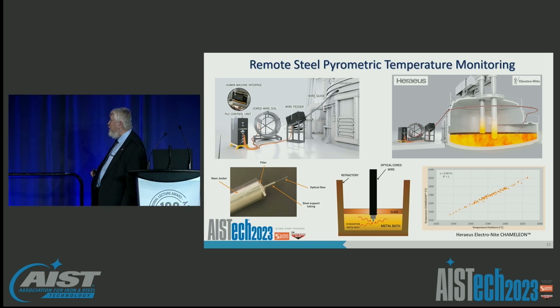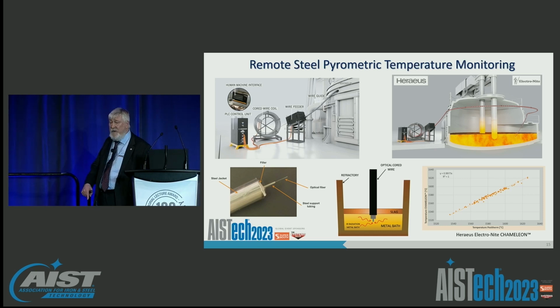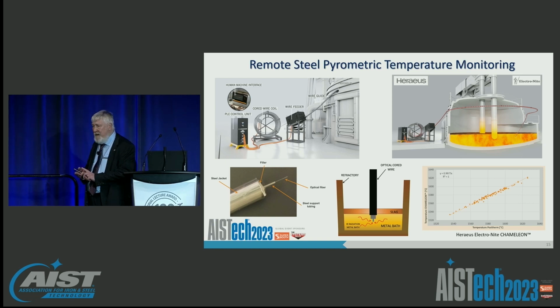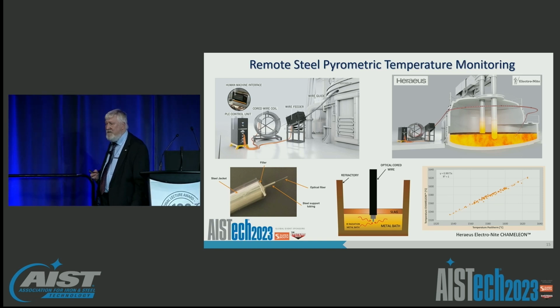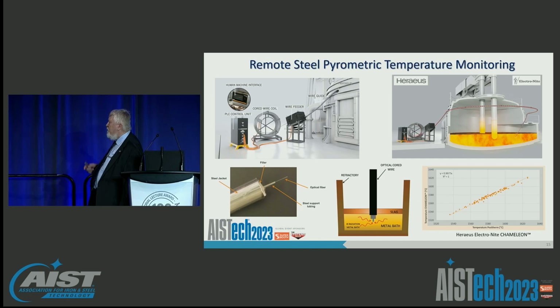There are some other advantages of this system. Because the fiber is being introduced and consumed, we can also do things like track interfaces, such as slag and metal bath heights in these systems. And we're working actually with Heraeus on some other ideas to incorporate composition measurement in these kinds of systems as well.